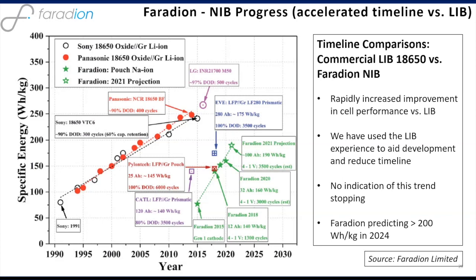And that's with no change in the cell chemistry, by the way. We'll be keeping the same chemistry, but just engineering the cell in a more efficient way to get to higher watt hours per kilogram. If we can get over 200 watt hours per kilogram, we move ourselves into a position where we're not far short of the specific energy performance and energy density performance for NMC and NCA. So we will do that obviously at lower cost and better safety.